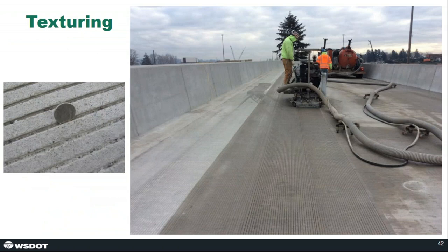So a note about texturing. As I mentioned, we used to texture the concrete while it's plastic, but now we finish the concrete smooth, and after the cure is removed, we provide a texture with a diamond grinder running longitudinally. You see that process here in this photo.